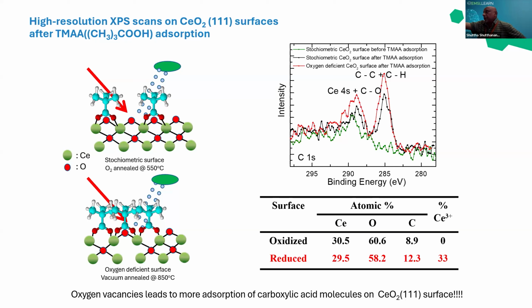And then the other one is coming around 289, which belongs to COOH bonds. But if you look at the reduced surface, you see that absorption is more. So for doing this kind of experiment, we can see the oxygen vacancies or the cerium 3 plus is promoting more absorption of these carbonic acid groups.